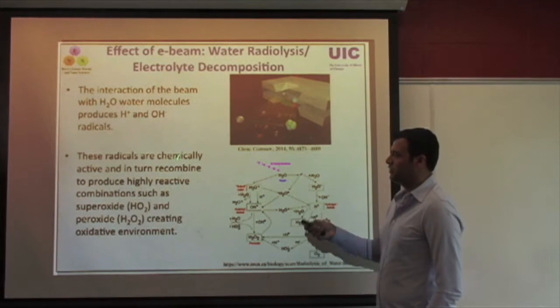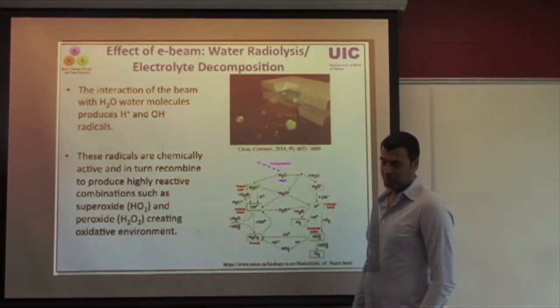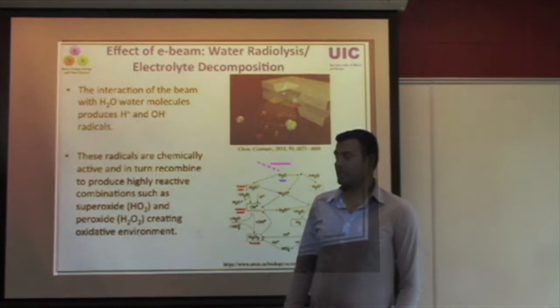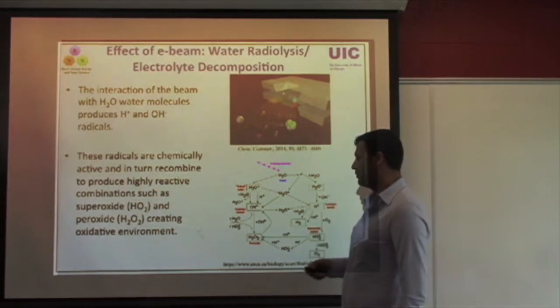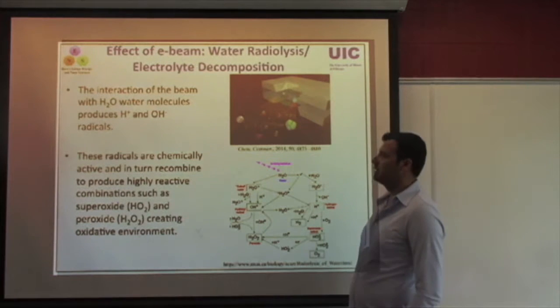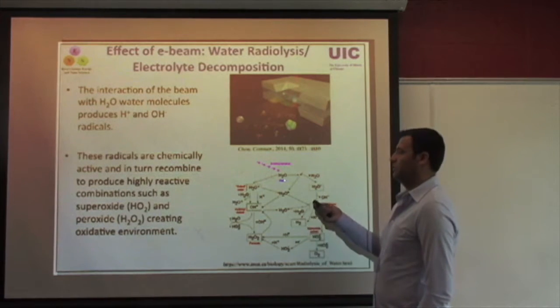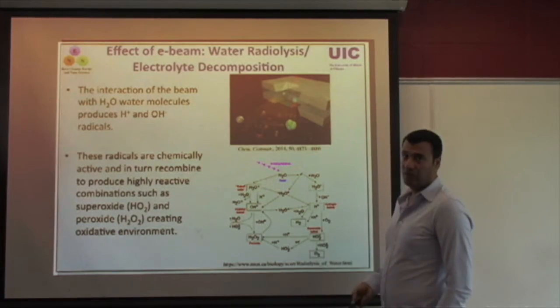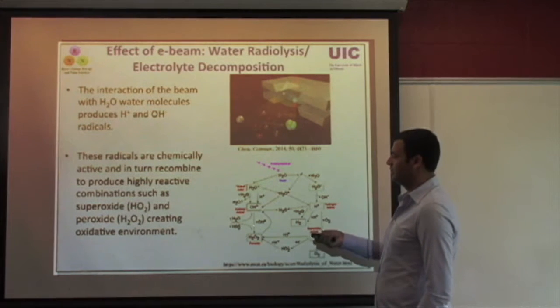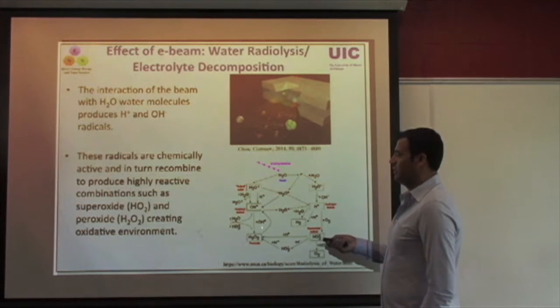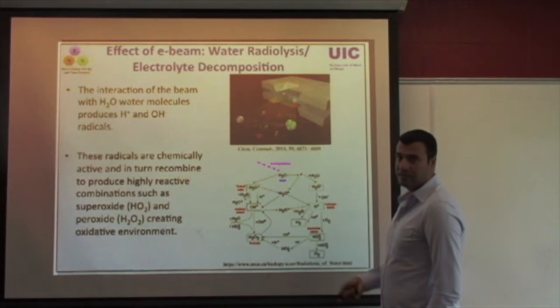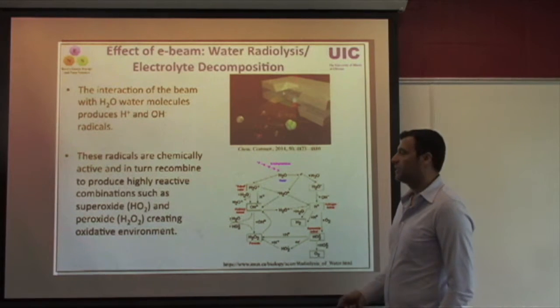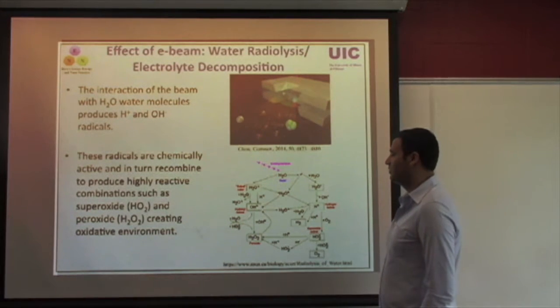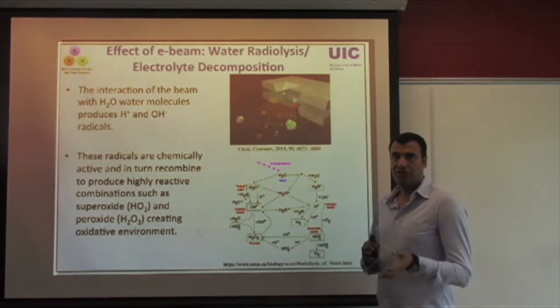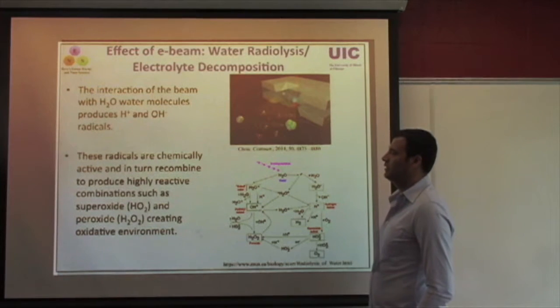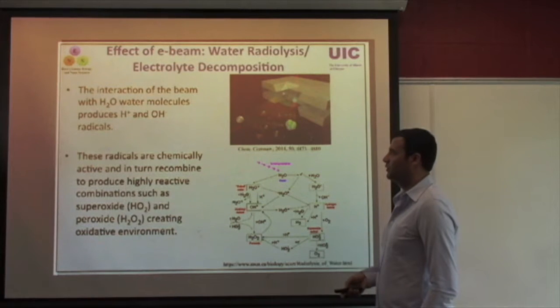Example of a big issue if you are dealing with a liquid electrolyte system, especially if it contains some sort of water. Then you might have radiolysis of water or decomposition of electrolytes, and during the radiolysis you might get lots of radicals, bubbles, and gas phases that are forming, and that might totally change the electrochemical study that you intend to do.